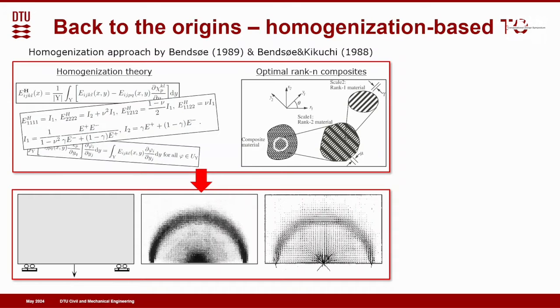But also, based on a lot of math theory by Bendsøe and Kikuchi, they knew the optimal microstructure. So if there's just one load case, we know the optimal microstructure is one that's oriented along the principal stress directions and with two layers that are adapted to the principal stresses. And with that, they came up with these pretty ugly looking structures at the bottom here, and that looked so ugly that it was essentially forgotten for many years.